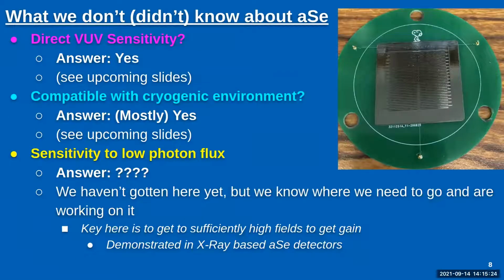So what we didn't know prior to some of the work that you'll see in this talk is the answer to, is amorphous selenium sensitive to direct VUV light? The answer is yes, as I'll show you in some upcoming slides. Is amorphous selenium compatible with a cryogenic environment? The answer is mostly yes. Again, some details coming. And is it sensitive to a low photon flux? There, we don't quite know yet. We haven't gotten all the way there, but we know where we need to go. The key here is to get a sufficiently high field so you can get gain. This has been demonstrated in X-ray based amorphous selenium detectors, but now we're trying to understand how to adapt it to our particular use case.